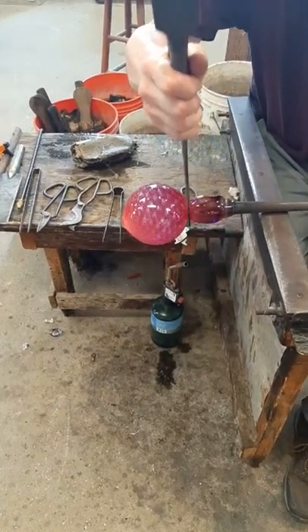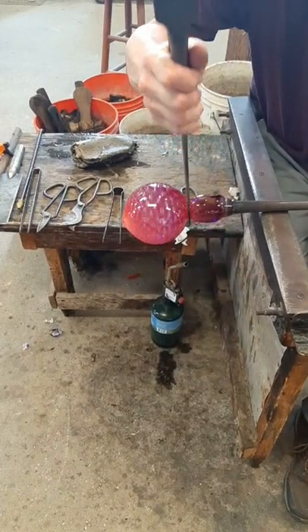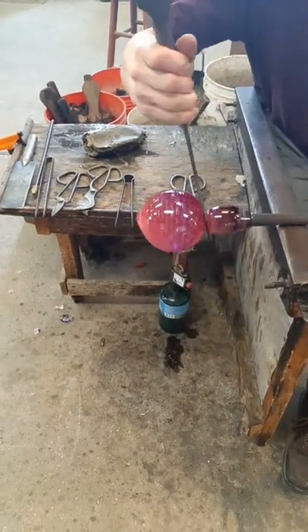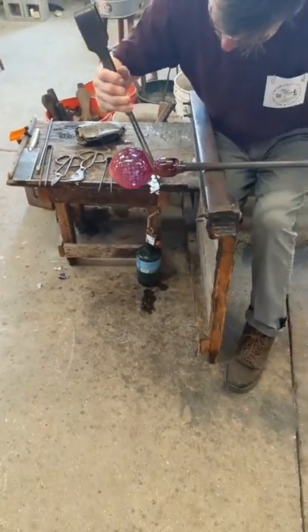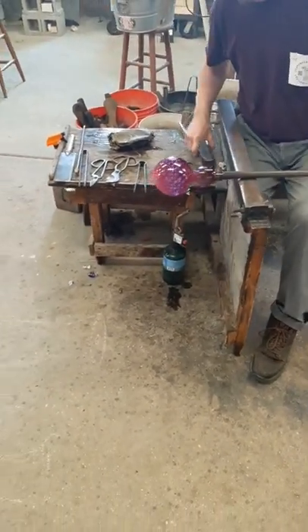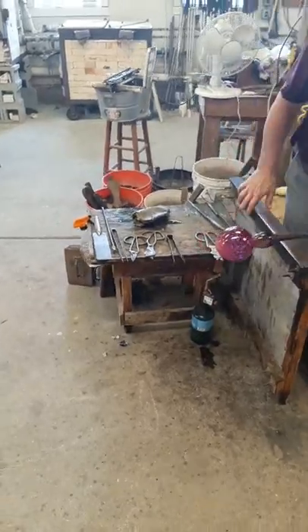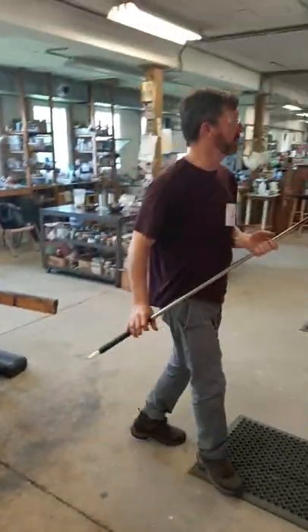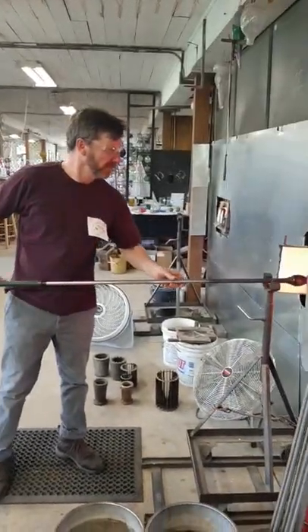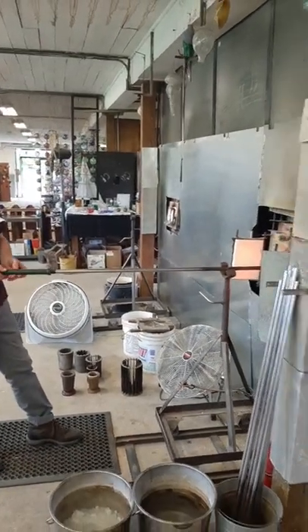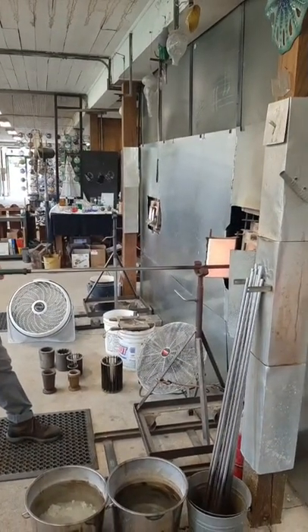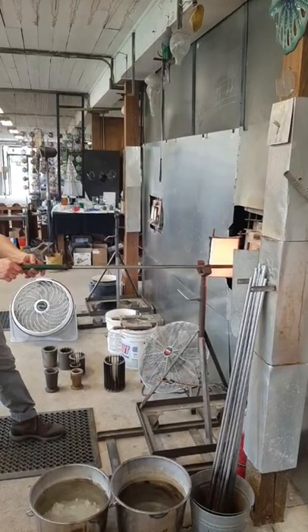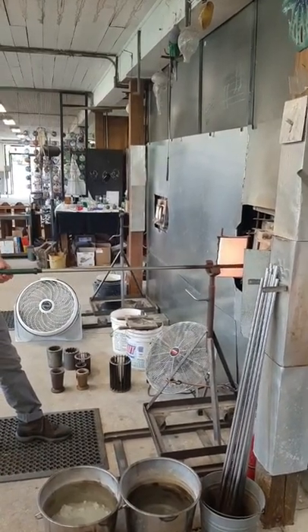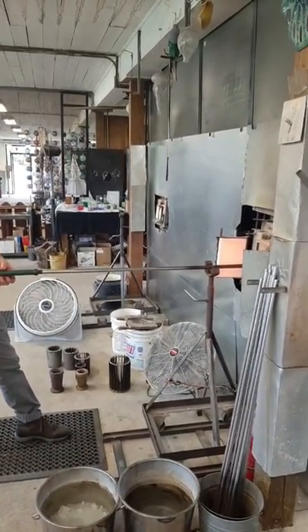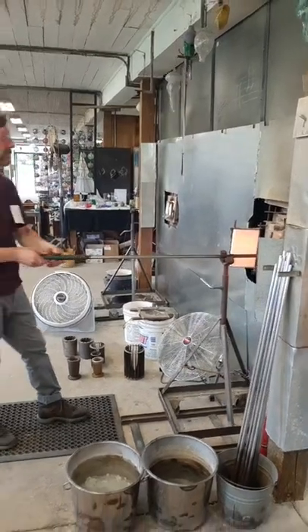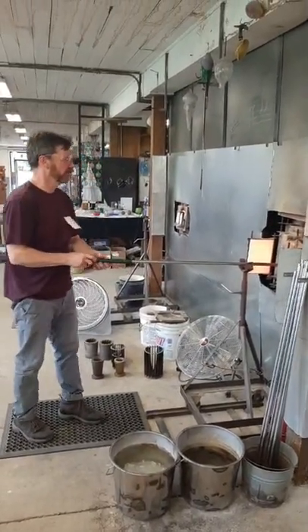See those beautiful bubbles in there. The cutting of the jack line is really important. If it's not a large enough diameter, it impacts the transfer, the break off, if you will. Because when we actually do that transfer and break the piece away from the blowing iron, there's a little bit of shock, transmission of energy, and the glass actually springs apart a little bit.